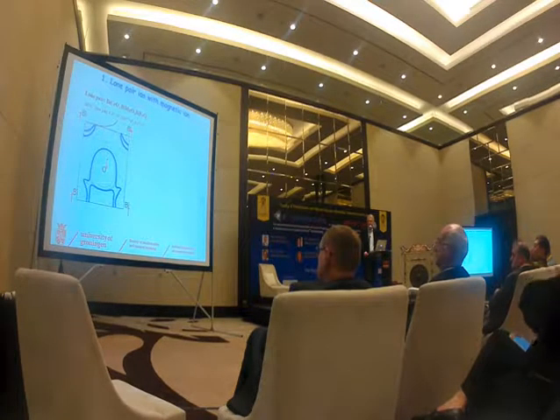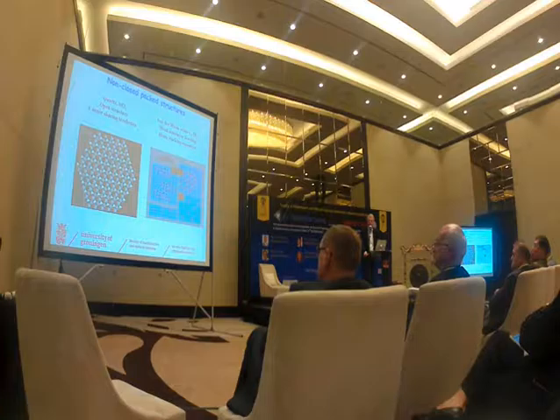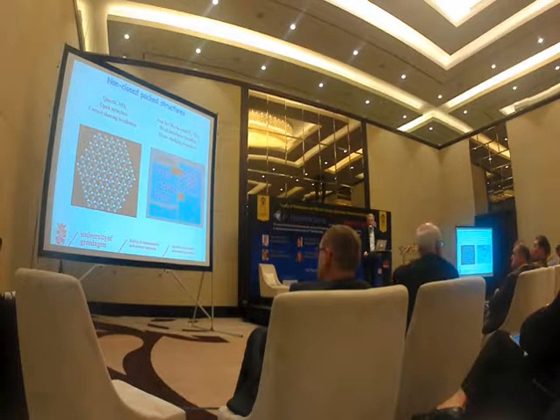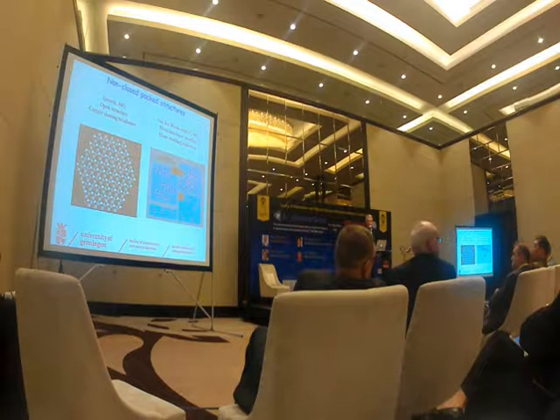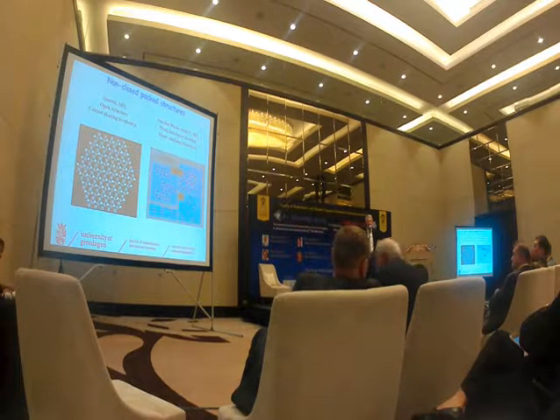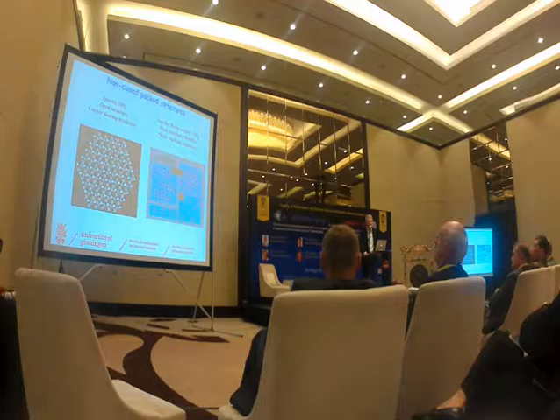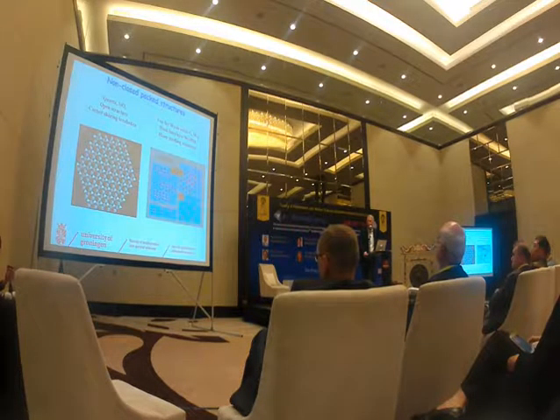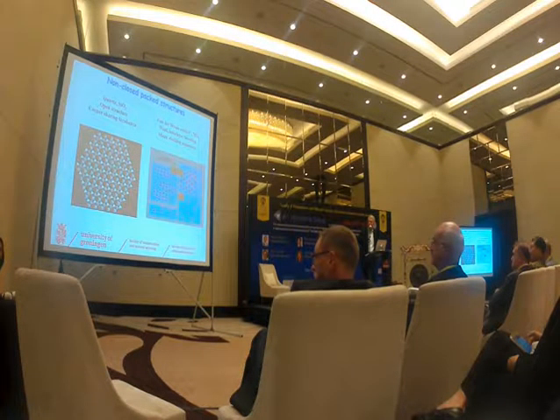The much easier way to do this is to use materials that do not have dense packed structures. And the easiest example of that one is quartz. Quartz, silicon oxide, is based on the tetrahedral coordination of silicon, and the tetrahedral coordination of silicon obviously does not have inversion symmetry. So here you see the crystal structure of quartz, where you see that it lacks inversion symmetry.